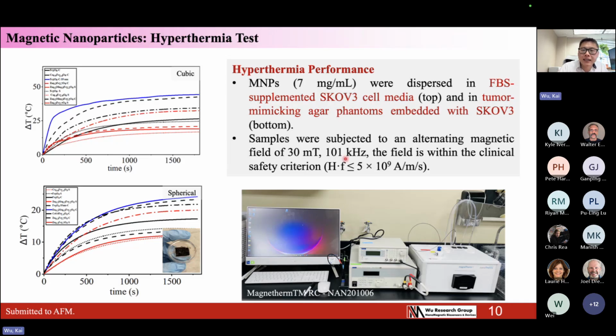When the particles are in the liquid, as in the top one, they are in the FBS buffer liquid with the cells. They can generate heat through the joint hysteresis loss and also the Brownian and Néel processes. So you can tell that when the particles are in the liquid, they will heat up the sample very fast. The delta T temperature increases to 40 degrees C in a short time. However, when they are embedded in an agar phantom, the Brownian motion is blocked. The heating can only reach 25 degrees C.